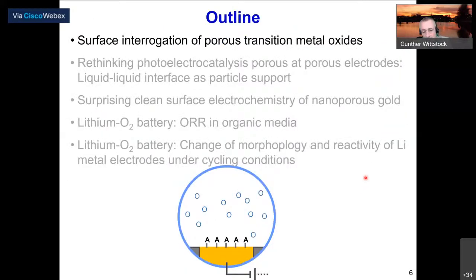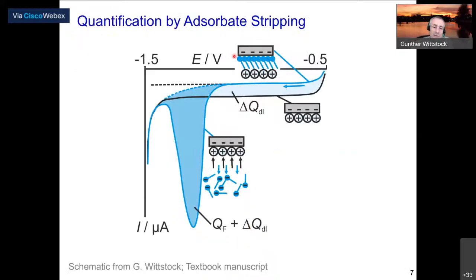So the first example I would like to bring to you are surface oxides at noble metals, and also transition metal oxides. They are extremely important for electrocatalysis, and we would like to investigate that. There are, of course, procedures already established for that, and one procedure is based on the oxidation or reduction of adsorbates, like adsorbate stripping. One procedure is known as carbon monoxide stripping, or here that is probably more related to the stripping of alkanethiolate layers from noble metal electrodes. So we have a baseline, we put charges in these molecules, they desorb as alkanethiolates, for instance, or in case of CO stripping, we oxidize it to CO2.